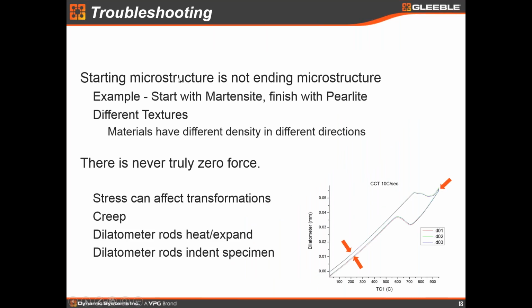The primary reason dilatometric loops don't always close is that the phase you end up with after doing a dilatometric experiment is often not the same phase that you started with. This graph actually shows three different curves, and they're very repeatable, so it's not a problem with the repeatability of the system. But I suspect I started with a sample that had a little bit of bainite or martensite in it. Then at 10 C per second, after I heated that, austenitized it, and recooled it, I probably ended up with a ferritic plus carbide microstructure. We all know that martensite has more volume than a ferrite plus carbide phase, so I suspect that's what's happening here. I don't know that for a fact.